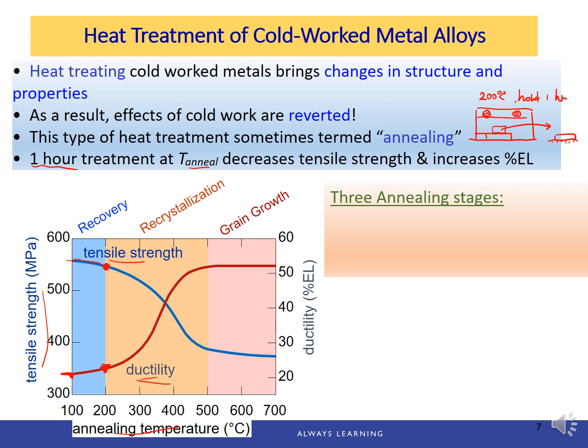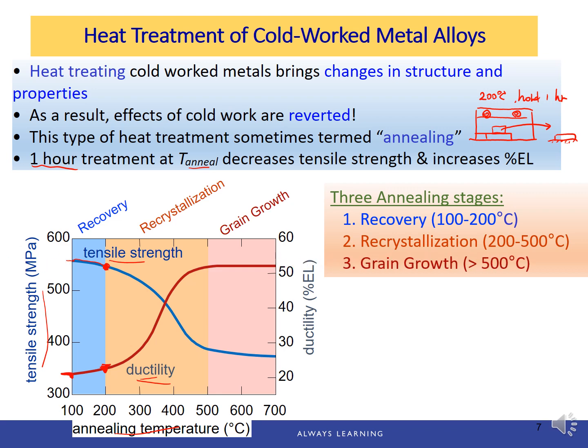There are 3 annealing stages. The first stage is called recovery, which usually happens between 100 to 200 degrees Celsius. The second stage is recrystallization, between 200 and 500 degrees Celsius. And the last stage is grain growth, which is usually above 500 degrees.